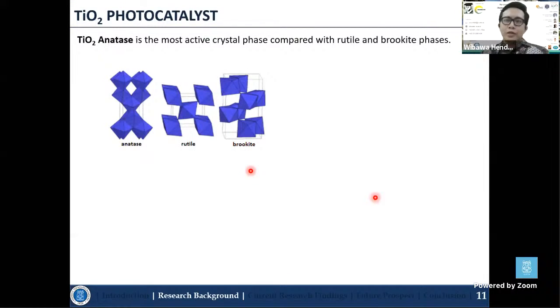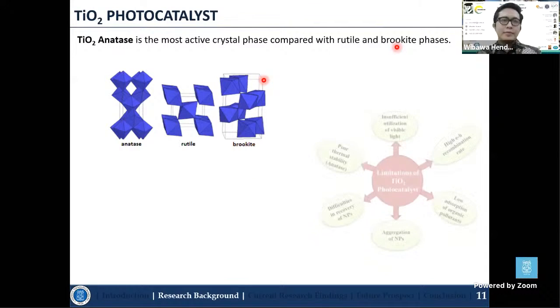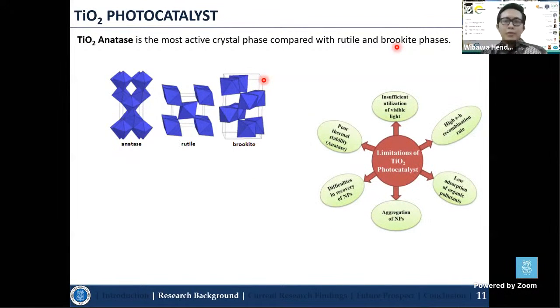So among semiconductor catalysts, titanium dioxide is actually the most common catalyst that is used, and also among the crystal phase, they actually consist of 3 different crystal phases, which is anatase, rutile, and brookite. So the titanium dioxide anatase is actually the most active crystal phase compared with the rutile and the brookite phase. However, the titanium dioxide has limitations such as insufficient utilizations of the visible light due to the large band gap. So it's around 3.2 electron volts, the aggregations of the nanoparticles, and also the low adsorptions of the organic pollutants.